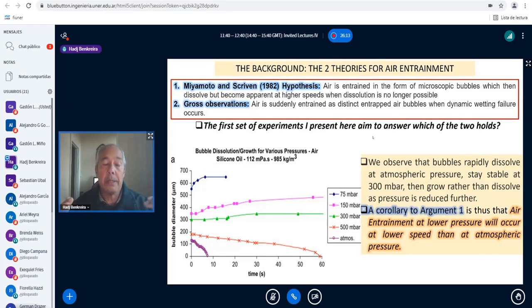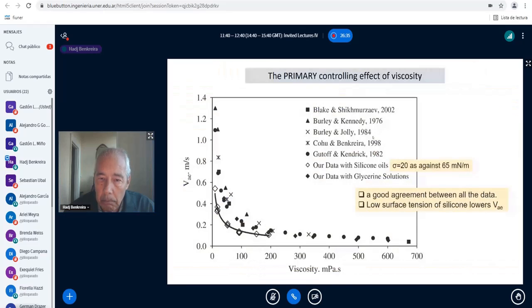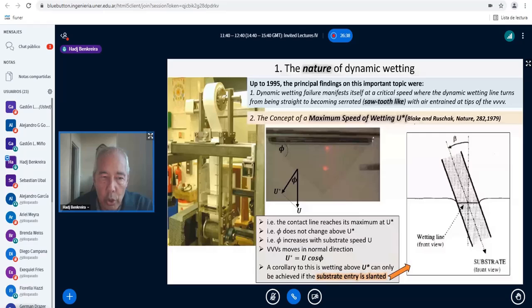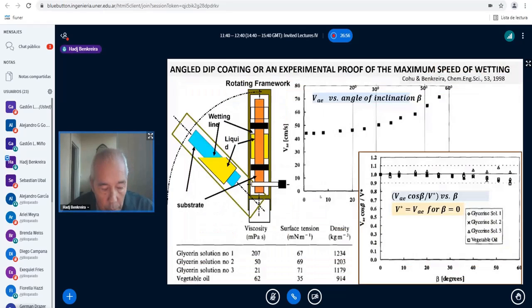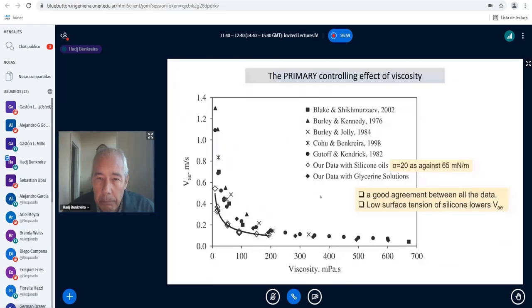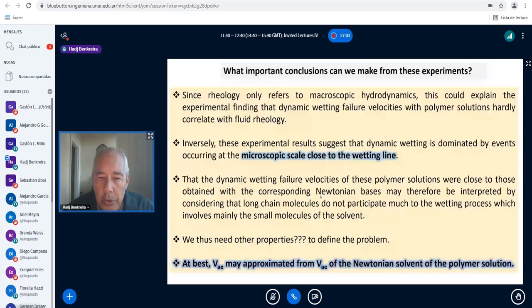The other hypothesis, which is based on looking at it grossly when you look at the V lines, is that air is suddenly entrained. It's only when you go above a certain velocity, you will have the situation that I have described earlier, which is this one. You will turn from a straight line into a line which is made of V's, and at the apex of the V's, the air is entrained. So it has nothing to do with dissolution of the air into the liquid. So the first thing that we wanted to do is to say which of these two theories really holds.